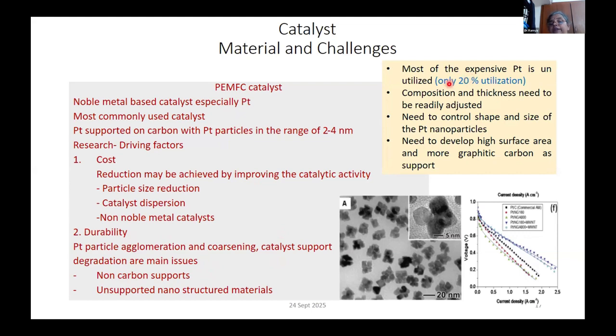If you look at the catalyst electrode, platinum is very expensive, and out of all the catalyst that you have coated, only 20% is active. So catalyst dispersion and particle size reduction become important for that 20%. And you have to adjust the composition and everything to get maximum performance. And with platinum on carbon, you are adding carbon, which is non-reactive actually. So there can be resistances because of this carbon support.